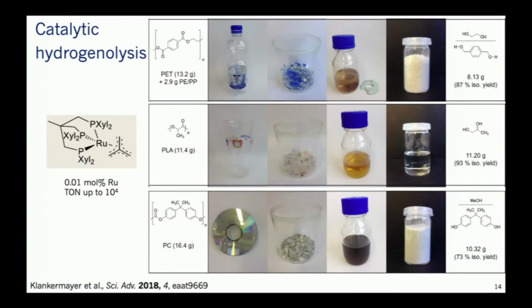In the case of these types of polymers, it's also possible to use processes which are thermodynamically more downhill. And in this case, rather than simply doing an alcoholysis, one can do a hydrogenolysis, cleaving the bonds that link the monomer units together using hydrogen. A different kind of catalyst is required here, one that will activate hydrogen. And in this particular example from Klankermayer in Aachen, ruthenium was used. So again, taking polyethylene terephthalate and cleaving those bonds, but doing reductions at the same time, the reaction proceeds very nicely. And even with post-consumer plastics that are mixtures and that contain labels and dyes and things like that, you can get very nice pure products out of these. They're not, in this case, the original monomers, but reduced forms of them in high isolated yields.